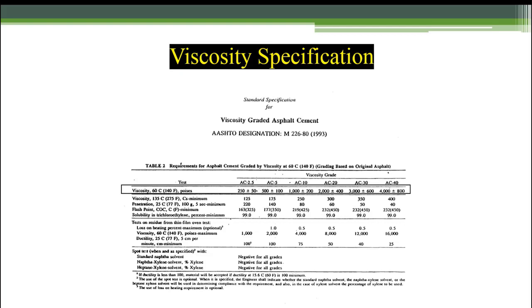Then you kept putting all these roads down with AC 20. What happened now? Now you started getting thermal cracking, cold temperature cracking. And now the maintenance foremen were yelling, quit building cracked roads. So go to an AC 10, softer. Again, 1,000 Poises plus or minus 200 Poises. Well, you do that for a while, yeah, the cracking would go down, but guess what? Now you get rutting in high traffic areas, particularly the way we were controlling mixes, and there was no field testing, and it was all Marshall mix design. And so you can kind of see that, and as you walk down a little bit, you can see the viscosity at 275 degrees, which is more of a mixing temperature, transport temperature.